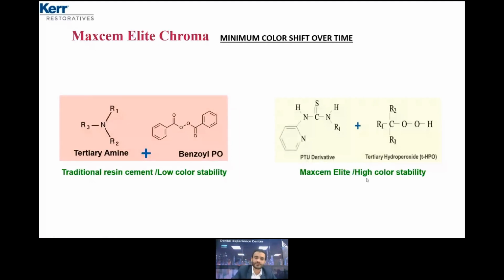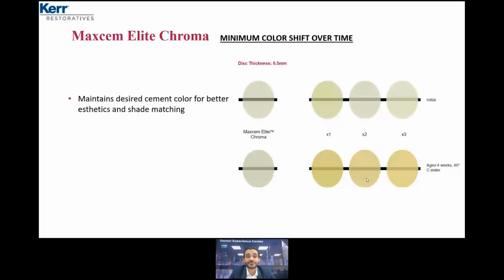Can we see an example of that? Yes. Here is the translucent shade of Maxcem Elite Chroma. The thickness of the disc was 0.5 millimeter. It was aged for 4 weeks at 60 degrees in water, and you can see before and after the amount of change. We have nil, or minimal, color shifting. On the right side, you can see another dual cure cement. They are very good actually, with high bond strength, which is great, but at the same time they have a yellowish discoloration and low color stability. So we need a balance between high bond strength and color stability of the cement.